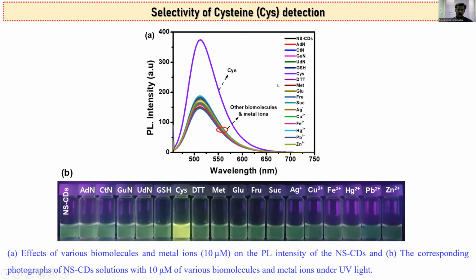Among the biothiol materials, only cysteine shows a strong interaction with the carbon dots, which significantly enhanced the photoluminescence from around 180 to a maximum of 380 or so. Other materials showed little or no change in photoluminescence. So it indicates that the carbon dots have high selectivity over other metal ions and other biomolecules. The cysteine molecule enhances the photoluminescence intensity more than other biomolecules and metal ions. We can see this from figures A and B. We can also calculate the increase in quantum yield, using quinine sulfate as the reference.